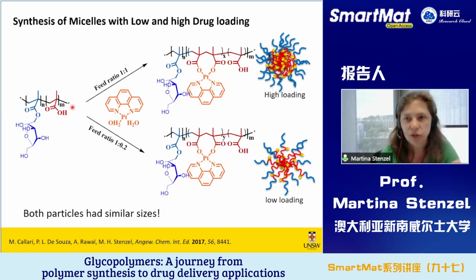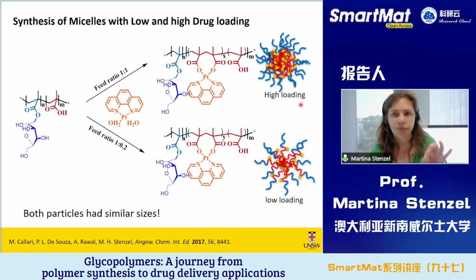We have done a whole range of studies in that regard, and I would like to choose one of these studies to show you that this is not always the case. We prepared two nanoparticles loaded with platinum drugs. One nanoparticle had a lot of platinum drug inside, so we called it the high-loading platinum drug. In the other case, we added less platinum drug on the inside, and we call it the low-loading drug. Both nanoparticles had very similar sizes, and you could not really see from the outside that there's any difference. At first, our hypothesis was that the high-loading nanoparticle should be much more efficient, for the simple reason that with every nanoparticle that is taken up, much more drug goes inside.